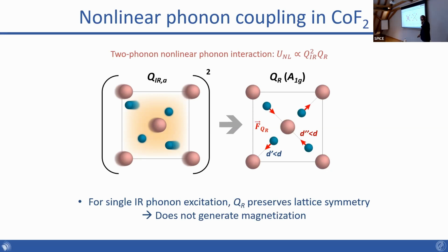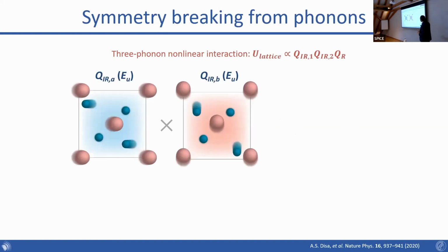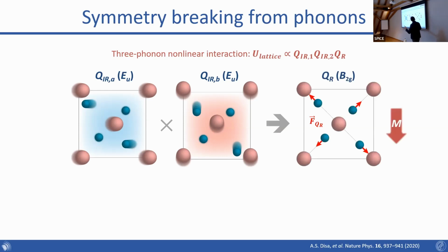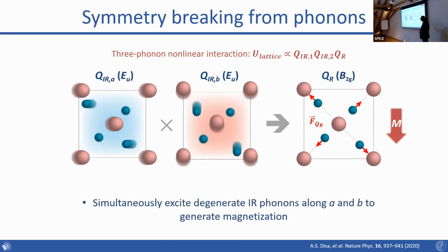So instead, what we have to do is use 3 phonons instead of 2. Okay, and we can use this 3-phonon interaction, which is more general, where we have 2 infrared active modes that couple to this Raman mode. And by symmetry, we can look at the group theory tables and show that if we have two infrared active modes of EU symmetry, so they're degenerate modes, but one pointing along the A axis, one pointing along the B axis, and we excite both of these simultaneously, we will then couple preferentially to this Raman mode with B2G symmetry. Okay, and so essentially, in order to realize this mechanism, I need to simultaneously excite two infrared active phonons with this symmetry in order to generate the magnetization.